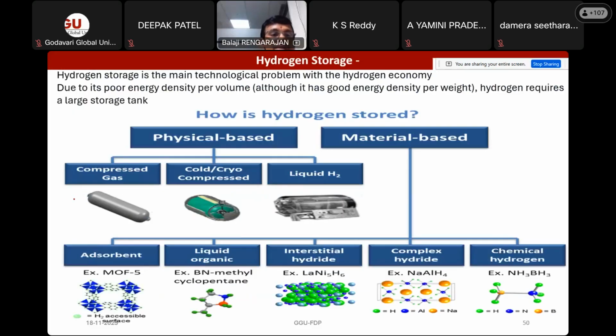So the compressed gas: because hydrogen is a lighter gas, the commercial hydrogen cylinder which we are using is a steel-based cylinder. In these cylinders, you cannot accommodate hydrogen at more than 150 bar because hydrogen has a nature of embrittlement in the metal matrix. It is a lighter gas, so when you try to compress it beyond 150 bar in a steel cylinder, it tries to penetrate the metal matrix and creates a kind of cracks within it, causing an explosion. So a steel-based cylinder cannot be used to store hydrogen at more than 150 bar.